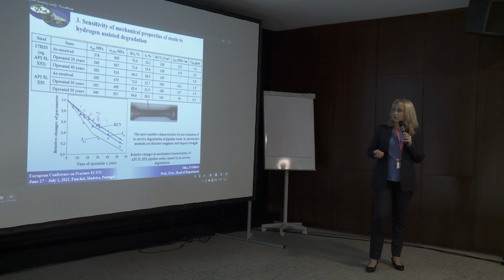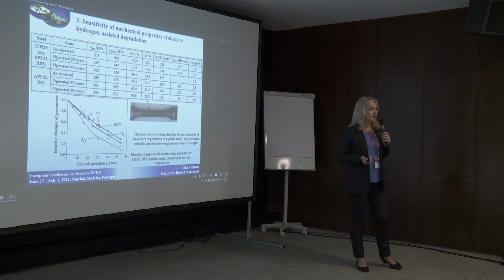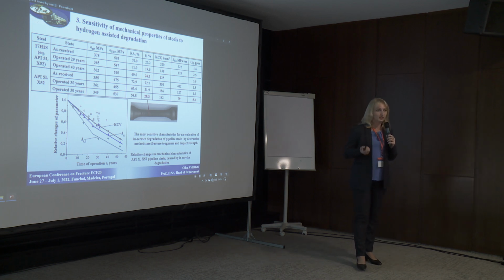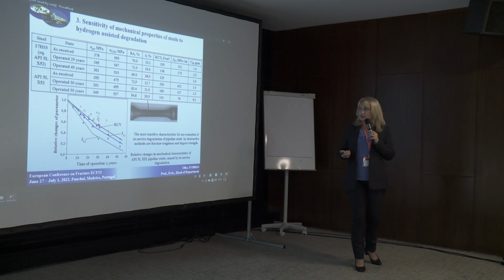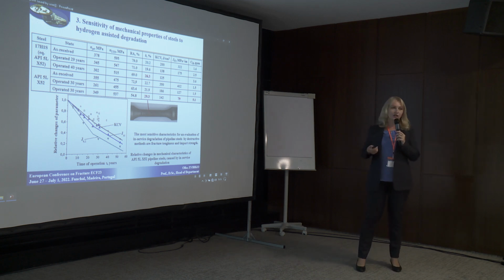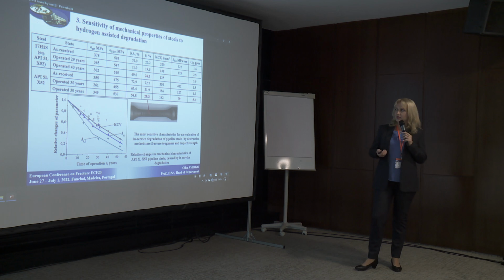I'd like also to note that elongation in the degraded steel can be even higher than that of the as-delivered one. And this phenomenon can be explained by development of dissipated damaging in steel under operation, and then degraded steel becomes sensitive to cracking under tension, and elongation will symbolize real plastic deformation and also opening of these multi-cracks.